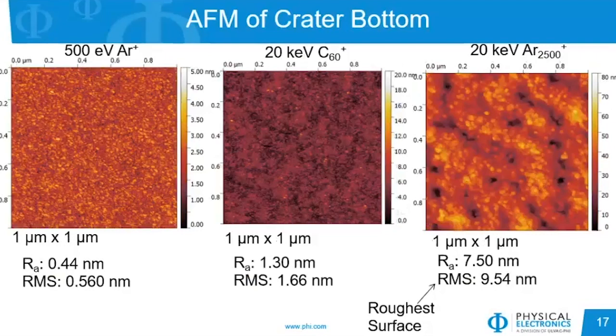We can also zoom into a smaller field of view of approximately 1 by 1 micron, and again we do see more structure in the argon gas cluster crater, showing that higher roughness.